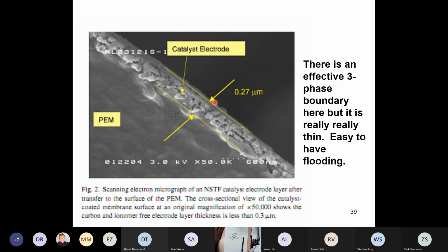space. Whereas the catalyst layer in a typical carbon-supported catalyst situation, carbon black with platinum nanoparticles, that catalyst layer would be more like 10 to 15 microns thick. So here you're generating all that water in this tiny little space, so it's really easy to have flooding. So these catalysts gave a really good three-phase boundary, but it's really tough to run these things without flooding. Any questions about this?